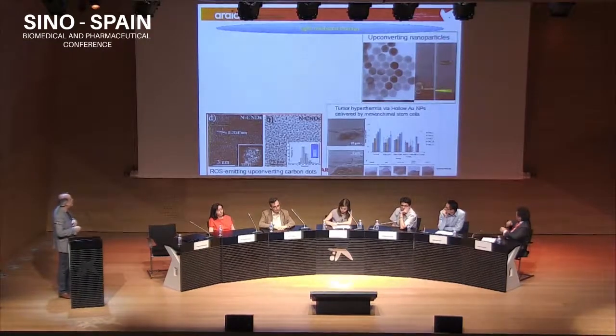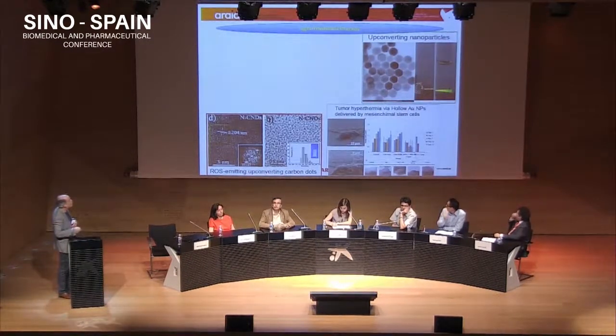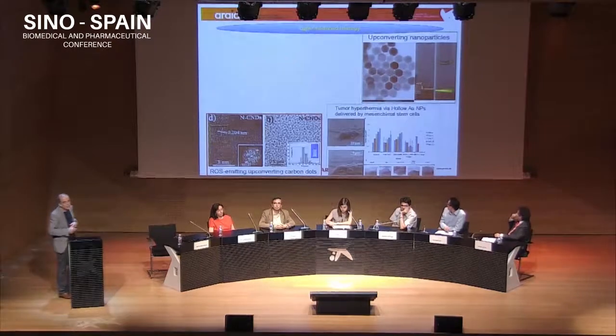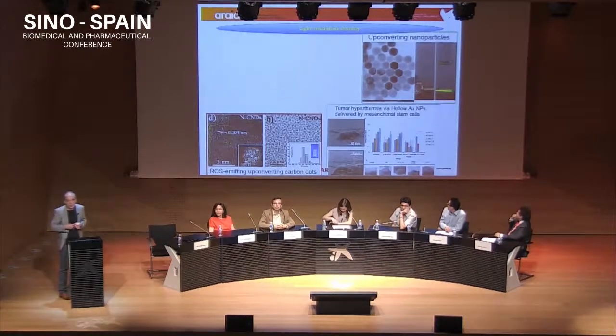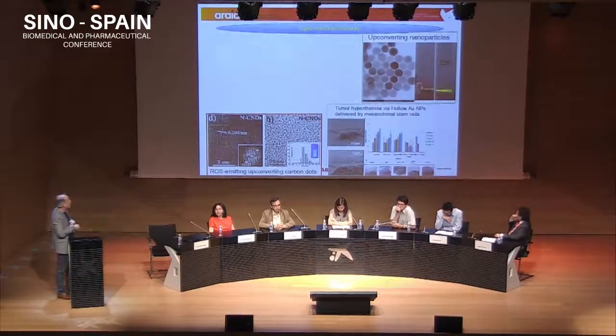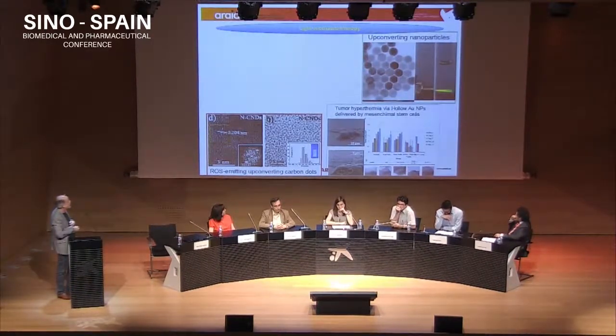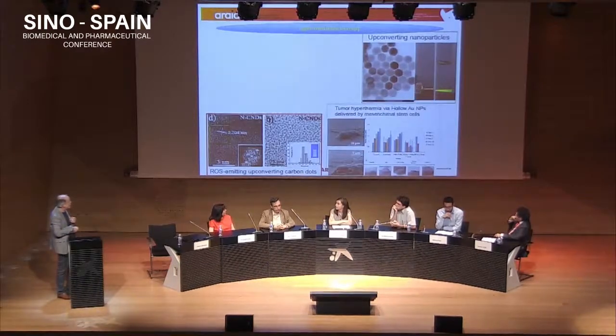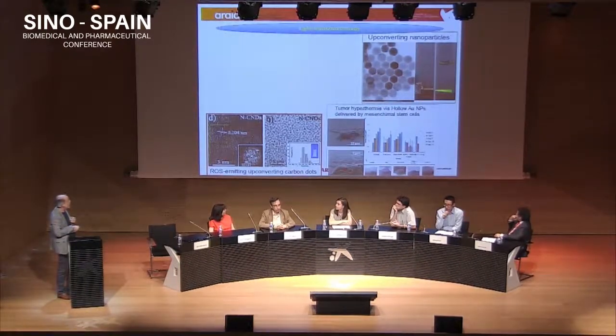Okay, this is tumor hyperthermia using the Trojan horse strategy that Dr. Martin Duque talked about this morning. This is something that we do in collaboration with her. So we load our nanoparticles in a mesenchymal stem cell. This is a mesenchymal stem cell. And when you cut it with a focused ion beam, which we can do in our laboratory, we cut it in half, and you see the nanoparticles inside, the gold nanoparticles. And then when you put them in a tumor, they stop tumor growth.